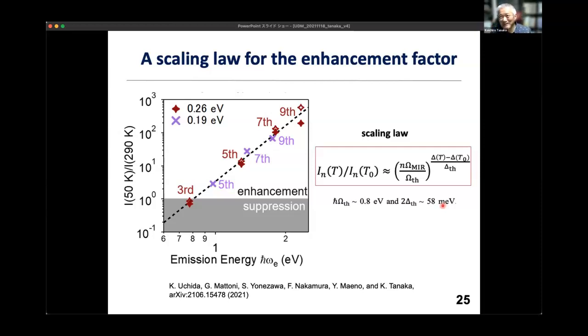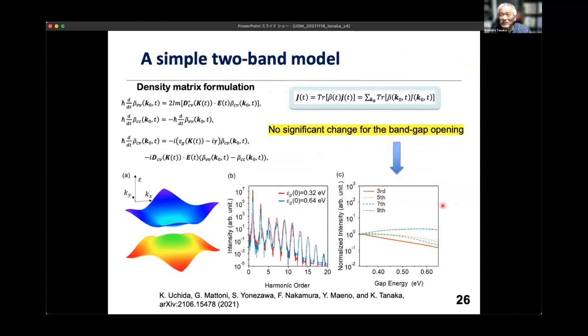Now we considered a systematic theoretical treatment, but we didn't. So we just did a simple two-band calculation for a cosine band. We did the density matrix formulation and calculated the harmonics, and just changing the gap energy, we calculated what's happening. But this is the result for this simple picture, a conventional semiconductor, and we have almost unchanged results, nothing significant. So our observation, a very large enhancement at low temperature, should come from electronic correlation or interplay between other order parameters.